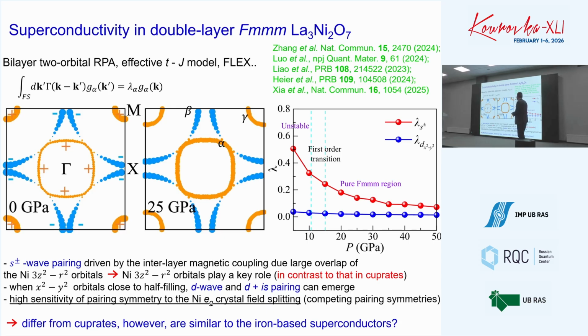But the main result is that for these materials we do have this S plus minus superconductivity, possibly with a mixture with another state. This pairing symmetry is quite sensitive to fine-tuning somewhat, but I would say that the most common result now is that this is S plus minus superconductivity.